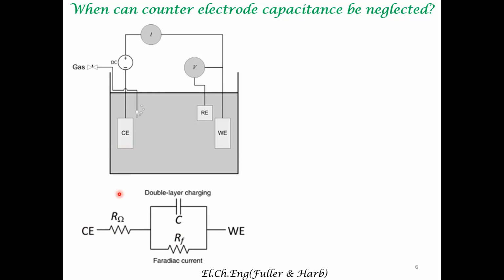We already said that the rate processes at the counter electrode should not impede the rate processes at the working electrode. That is, the electron transfer at the counter electrode should be facile compared to the electron transfer at the working electrode. One way to do that is to have a very large counter electrode, and it also has certain other advantages. Let's see what. If the counter electrode rate processes are much more facile compared to the working electrode, automatically the R_F corresponding to the counter electrode becomes negligibly small. Then we are left with the considerations of double layer capacitance at the counter electrode-electrolyte interface.